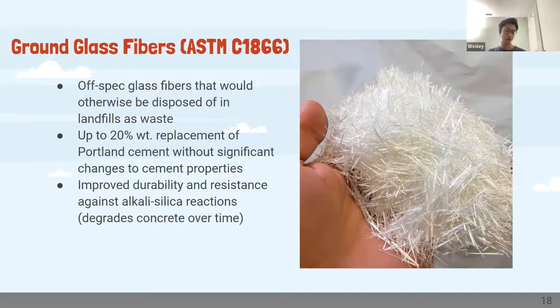And it also, on top of that, improves durability and resistance against alkali silica reaction. Essentially what alkali silica reaction, or ASR in short, is, is that the alkali from cement can react with the silica from aggregate, which is what you use to create concrete. Within the pores of the concrete, it creates something called ASR, or alkali silica reaction gel, and it swells up and causes the concrete to expand and eventually crack. So obviously this degrades the concrete over time and is bad.